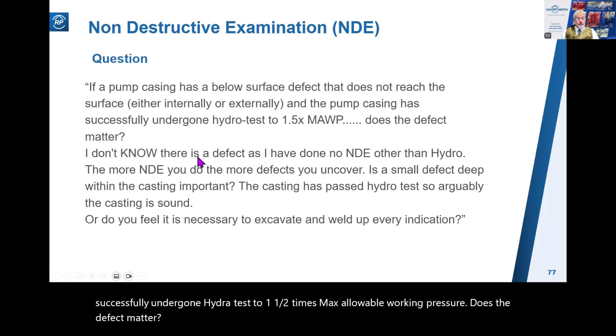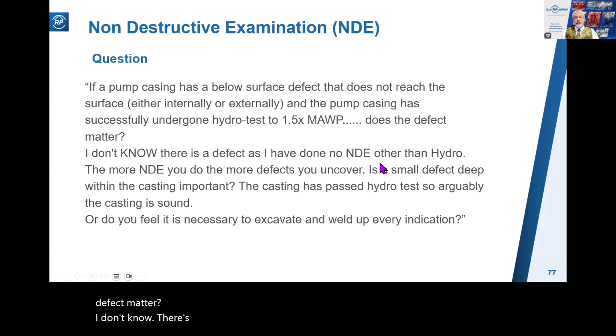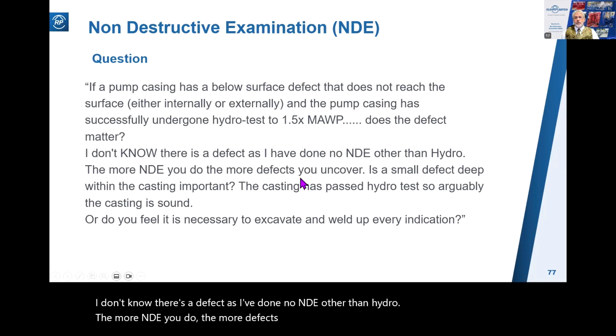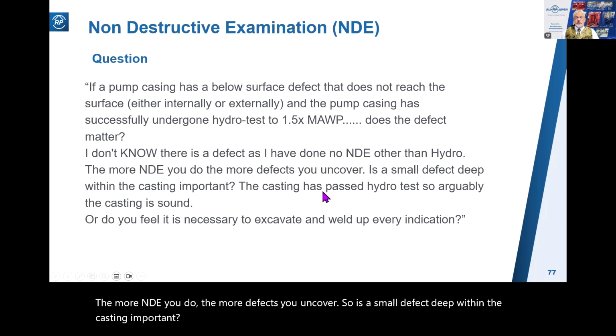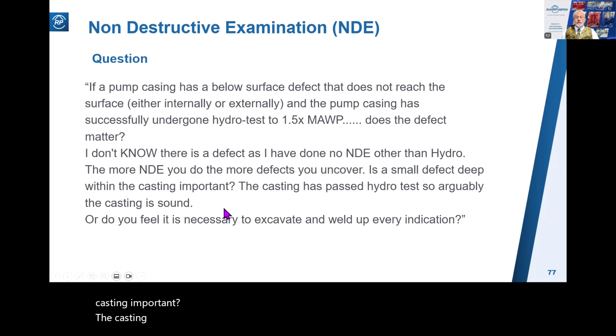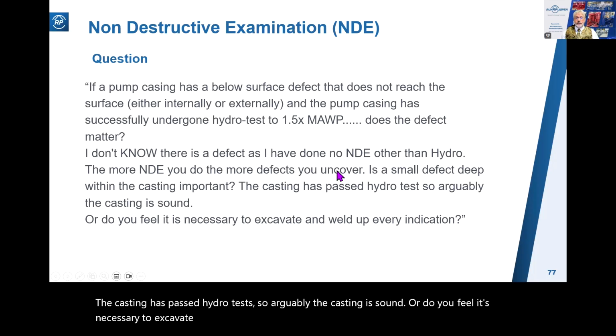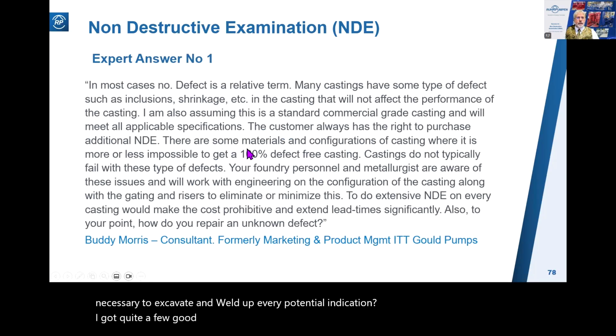I don't know there's a defect, as I've done no NDE other than hydro. The more NDE you do, the more defects you uncover. So is a small defect deep within the casting important? The casting has passed hydrotest, so arguably the casting is sound. Or do you feel it's necessary to excavate and weld up every potential indication? I got quite a few good answers, and I'll show you 2 of them.